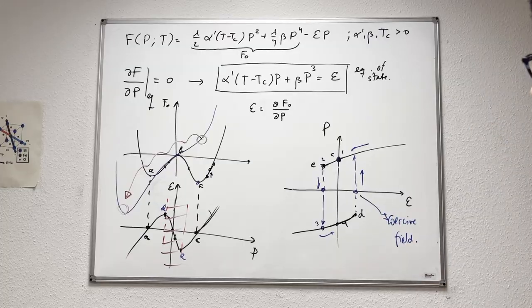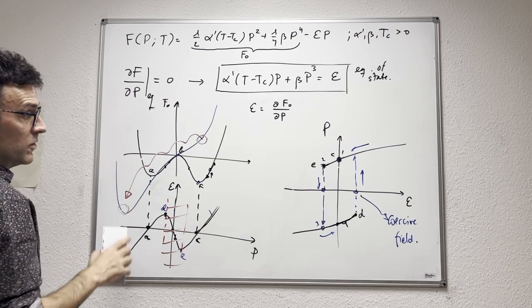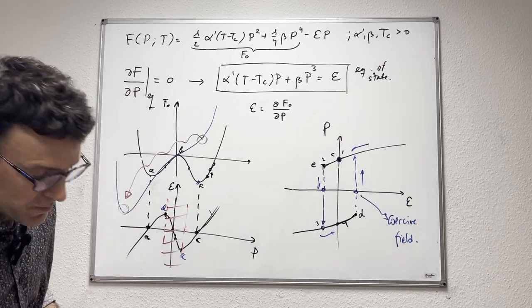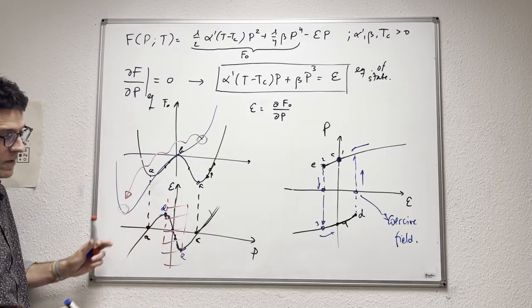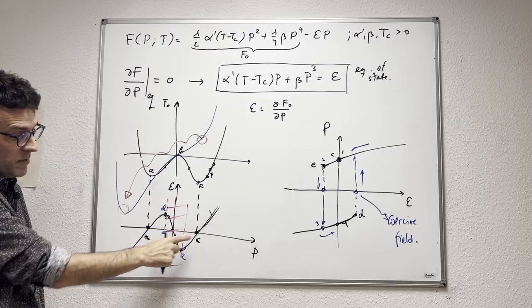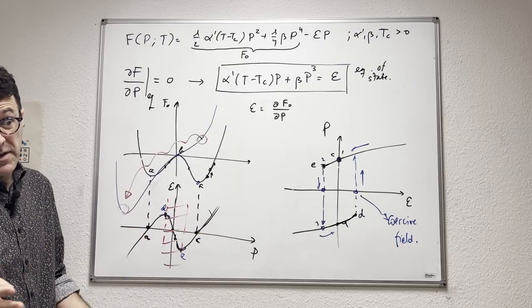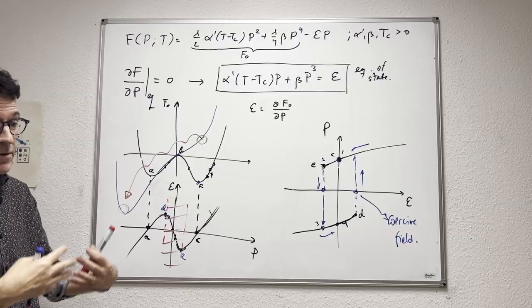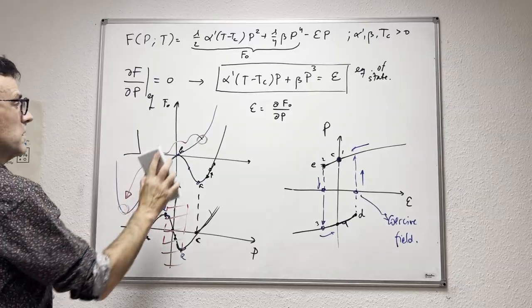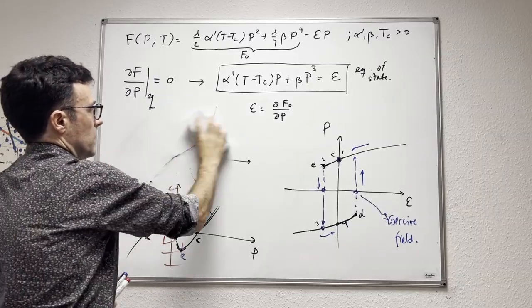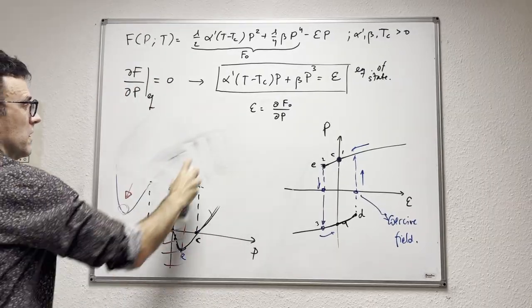One thing that one can think of, even though we haven't done any math, is that the coercive field in particular is very simple to calculate, right? Because the coercive field essentially corresponds to these points where the derivative of the electric field with respect to polarization is 0, meaning that the stiffness coefficient is 0. The stiffness needs to be positive for stability, so when it becomes 0, we lose the stability, right? So essentially, for completeness, I'll just indicate how we could compute the coercive fields from the theory.